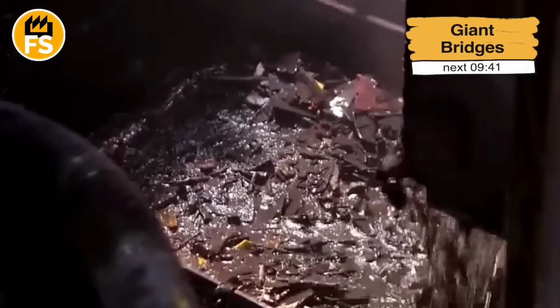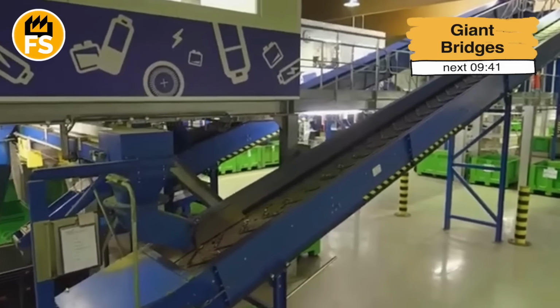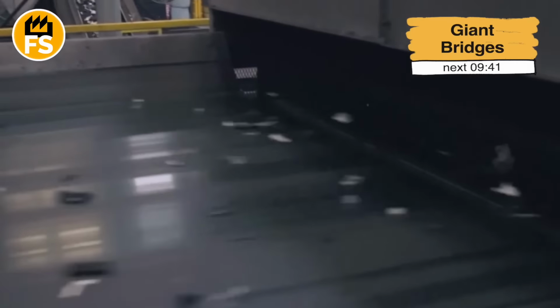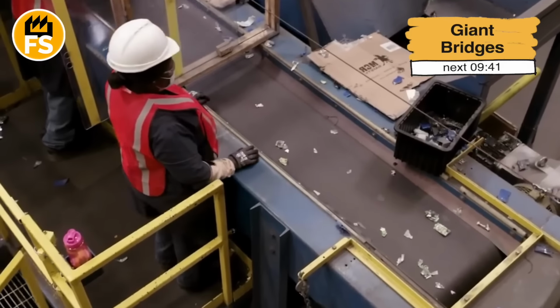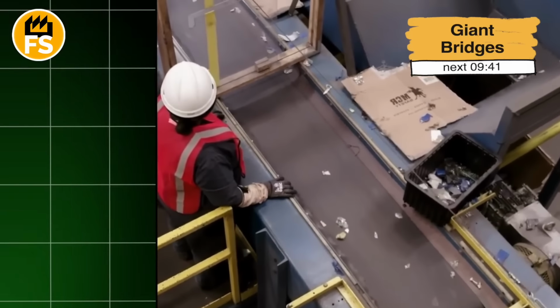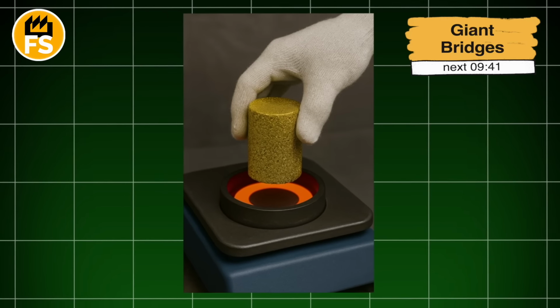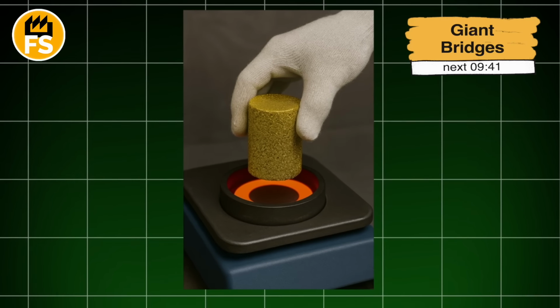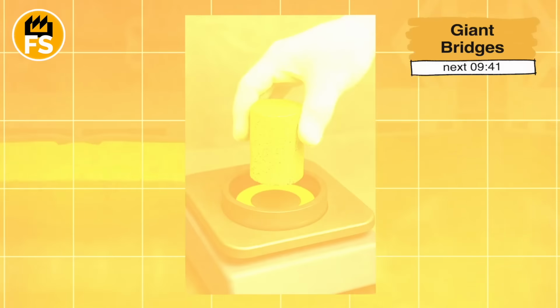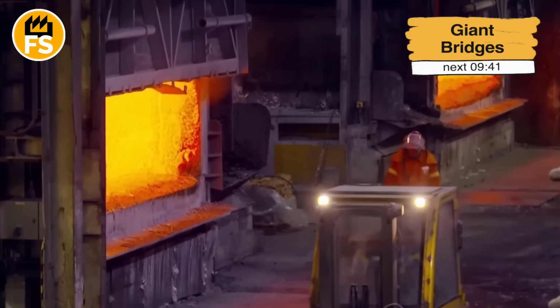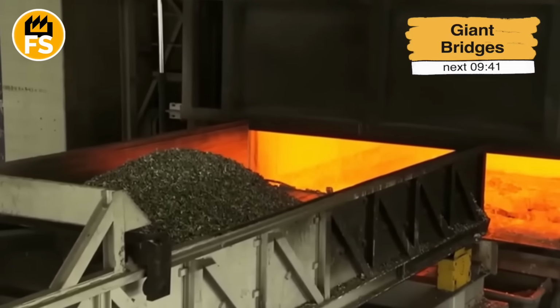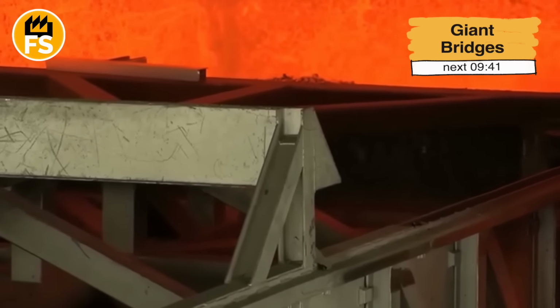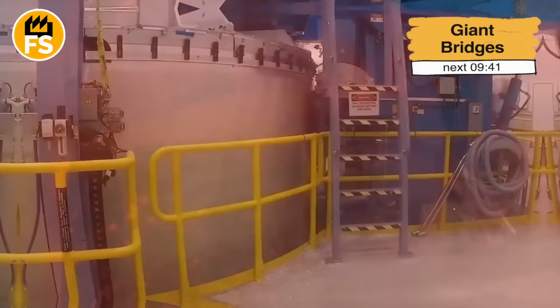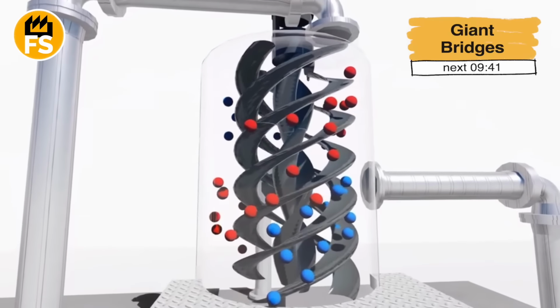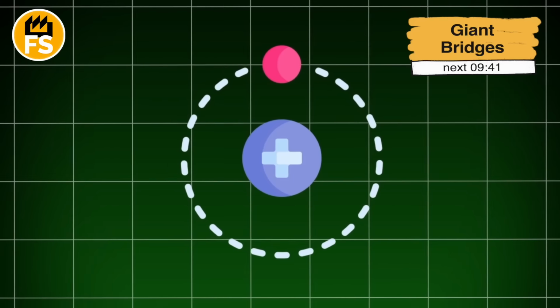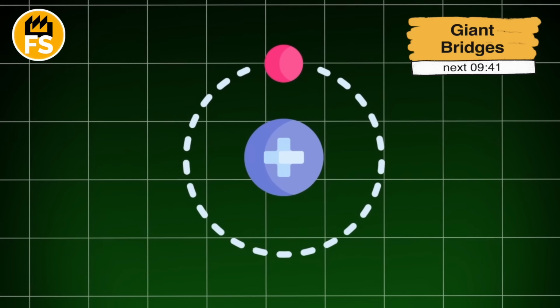For large volumes of gold-bearing concentrates, especially if they contain a significant amount of copper or other base metals, high-temperature smelting is used. The concentrated powder or fine granules may first be sintered or briquetted for more convenient feeding into the furnace and to reduce dust losses. The material is loaded into special electric or induction furnaces. Temperatures can reach 2,500 degrees Fahrenheit. During smelting, lime or silica is added, which reacts with oxides and other non-metallic impurities, forming a low melting slag.